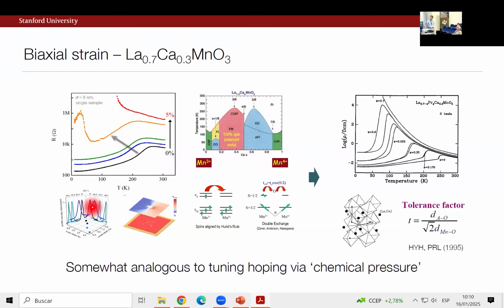This is now a grazing incidence scan in the two directions. So there's a little bit of a jitter here, but this was us trying to go down this diagonal direction. You can see that, going from 0, 1, 2, 3, 4% or 5% strain, you can rapidly suppress the metallic phase all the way to base temperature and undergo a metal insulator transition.